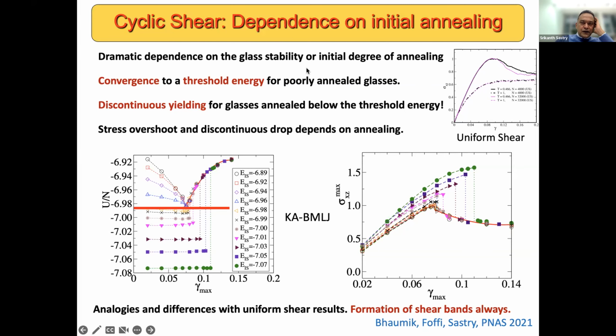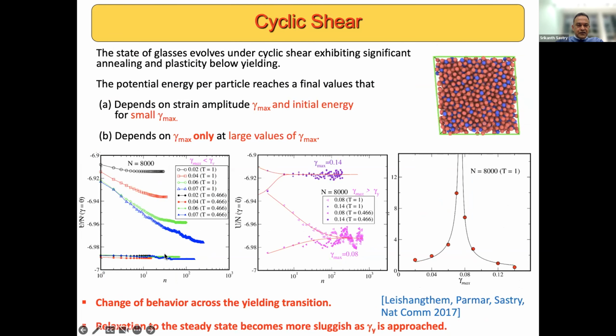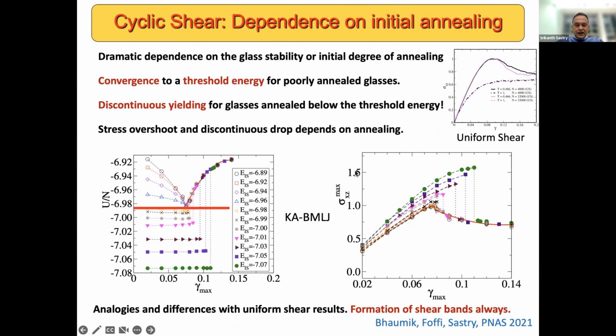Yeah, thanks. Okay, so now let me come to something that I've mentioned from the beginning, which is the importance of annealing, or the stability of the glass, on the yielding behavior. And this I show here under cyclic shear, where on the left and the right panels, what I'm showing are respectively the energy and the maximum stress that is reached at the end of the transients that I talked about here. If I keep watching, eventually I reach some final energy or stress, and I'm plotting those in this graph as a function of the initial energy of the glass as well as the strain amplitude.